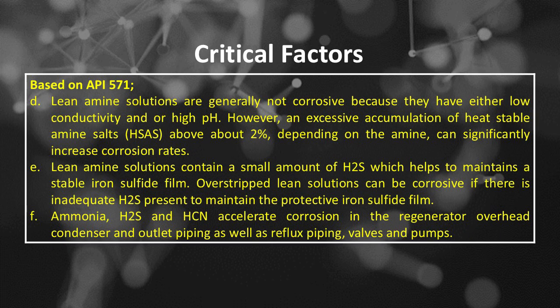Critical factors. Number D. Lean amine solutions are generally not corrosive because they have either low conductivity and/or high pH. However, an excessive accumulation of heat-stable amine salts, HSAS, above about 2%, depending on the amine, can significantly increase corrosion rates. Number E. Lean amine solutions contain a small amount of H2S which helps to maintain a stable iron sulfide film. Overstripped lean solutions can be corrosive if there is inadequate H2S present to maintain the protective iron sulfide film.